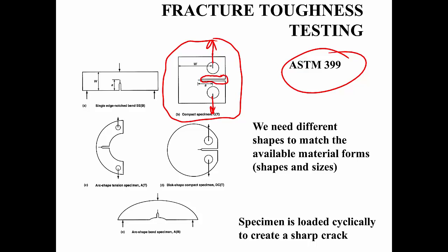It has a machined start of a crack, but that's not the end of the specimen preparation. The important part of the specimen, actually, is an actual crack that propagates at the tip of the machined slot there, and this crack has to be sharp. If that crack is not sharp, then we're going to have problems similar to the ones that are common for the Charpy test.